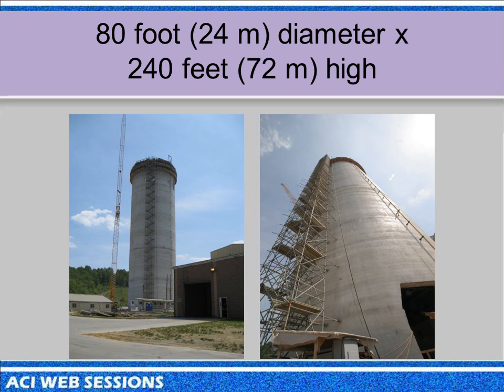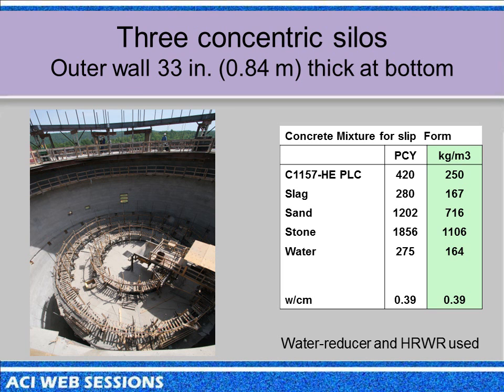That just shows this thing. It's 80-foot diameter and 240 feet high, slip-formed. And there's actually 3 silos, one inside the other. You can see it here. There's 3 rings here. They're all slip-formed independently to make 3 concentric silos. That's the mix design, so you can see that they've replaced a lot of the cement with slag. And then of that 420 pounds of cement, 10% of that was limestone.